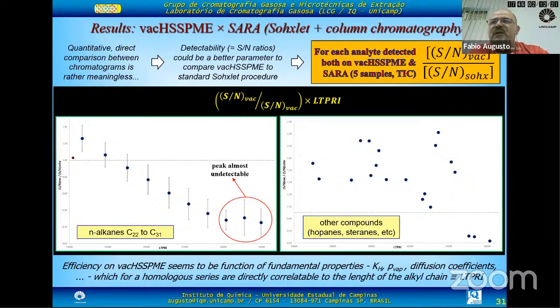This is the relationship between signal to noise ratios for peaks in vacuum headspace and Soxhlet extraction as a function of the retention index of the peak, which is related to the length of the hydrocarbon chain. As you increase the hydrocarbon chain, of course, headspace solid phase microextraction becomes less favorable. But remember that we are replacing a technique that takes 10 days to obtain the results. This is for hydrocarbons. For other compounds, there is not such a clear relationship, but the structures are very varied. So in homologous series, there may be a tendency.